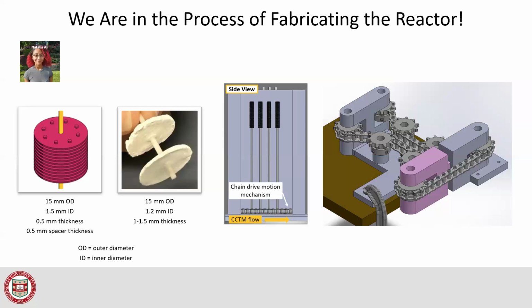So you can see there on the right, that's the reactor, or at least that's the guts of the reactor. And you have these materials moving around the reactor. At certain points, they're exposed to concentrated sunlight. They heat up and they lose oxygen. But at other points in the reactor, it's cold, and there's a source of water. So it's a continuous process.